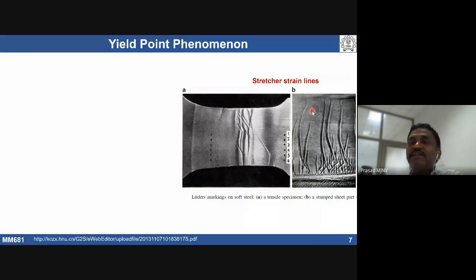The bands propagate, and one can see this macroscopically. If we use a well-polished sample, we can see the bands. With further deformation, those bands can give rise to stretcher strain marks. If you take a sheet of low carbon steel and stamp it, that can give us this kind of stretcher strain marks.